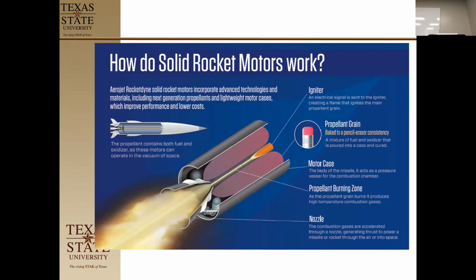Notice that right here you're going to have probably the grain, which is the combustible material, the propellant here, and it's going to burn first through here. So you have to have this as an ablative material as well, so that it doesn't burn through the case. But way up here, it's not going to be burning very long, so the protectant can be much thinner. You can actually just have the metal wall.